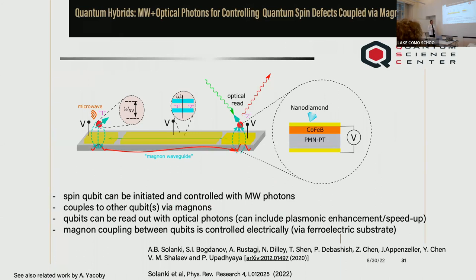So the hybrid quantum platform we are working with now is based on the following idea. You have this film, and then we're going to work with topological quantum materials, such as quantum spin liquid, like ruthenium chloride. But as a test, we first worked with a conventional magnetic film, such as YIG, and it supports magnons. Magnons are just collective excitations of spins. So what if, on top of this, you place nanodiamonds, for example, with nitrogen vacancy? They also have this local spin. So you could induce your spin with microwave photons. In this case, you could control it.